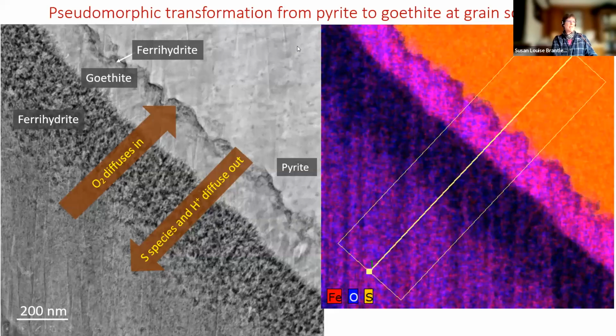And then you can go down even to a finer scale. Here's a TEM micrograph looking across. This is a cross section through one of these pyrite grains. Here's pyrite, and then here's iron oxides. And if you look at it at this 200 nanometer scale, it first changes to ferrihydrite, then it changes to goethite, and then it changes back to ferrihydrite with a lot of porosity in it. And so we don't understand why all those mineralogical transformations occur, but this is where the oxygen is actually diffusing in, and sulfur species and H+ have to be diffusing out.